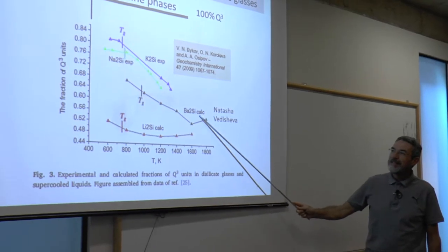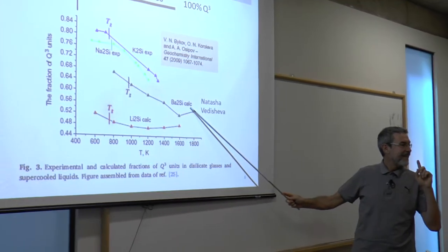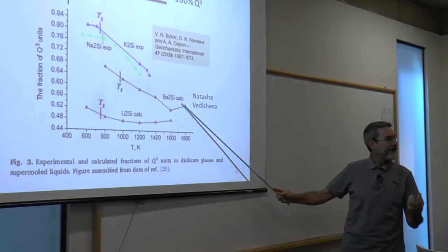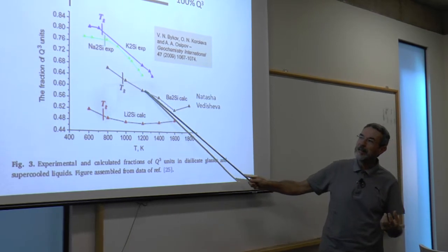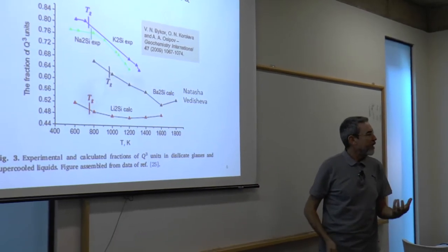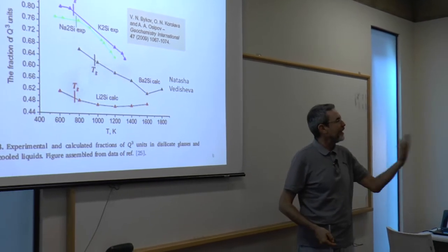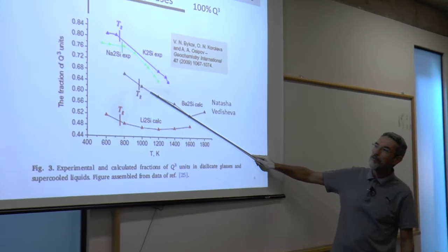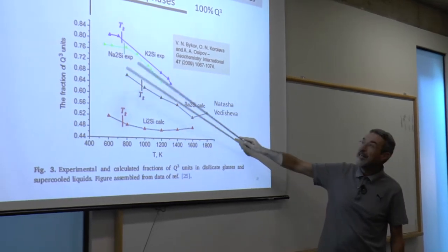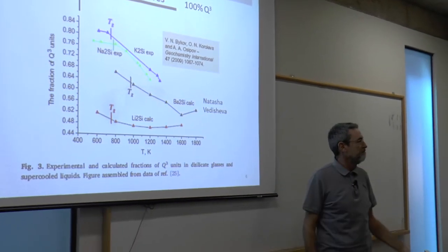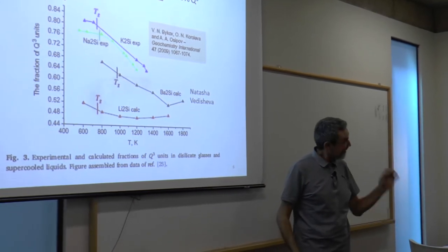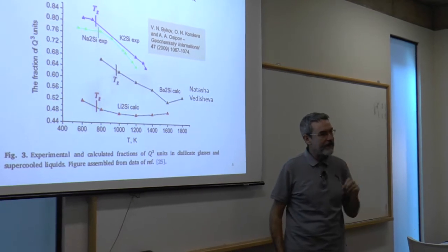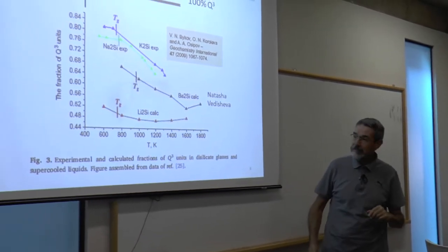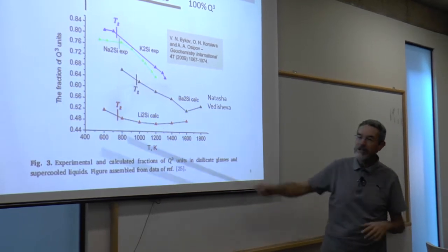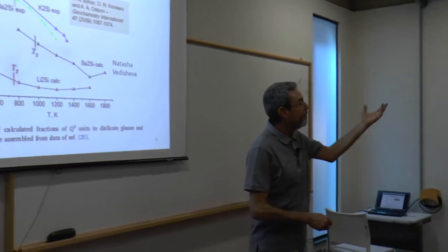Because of this. These are calculated from a thermodynamic model. This is only the calculated number of Q3 in this glass. So if you calculate, you don't see any Tgs, pure thermodynamics. So what we are seeing here is the supercooled liquid. These are experimental, see? Experimental. Then it freezes in. In calculations there is no Tg. So this is a very key question, and you perceived this. Thermodynamic calculations do not get it, because it's equilibrium.